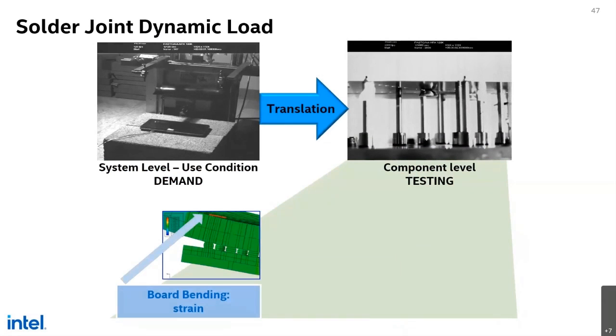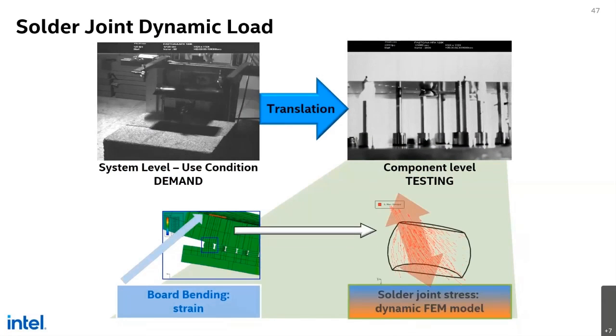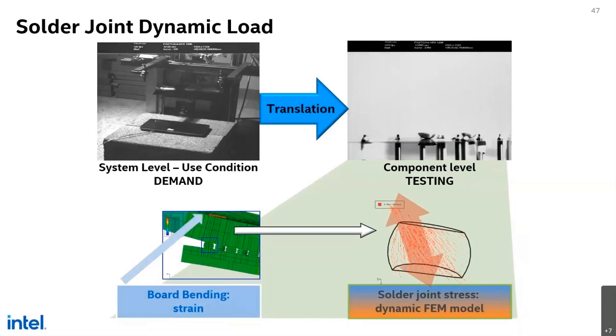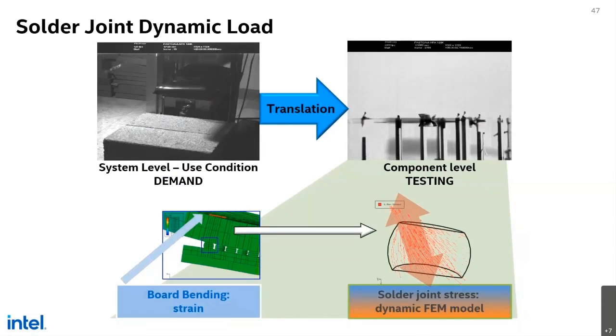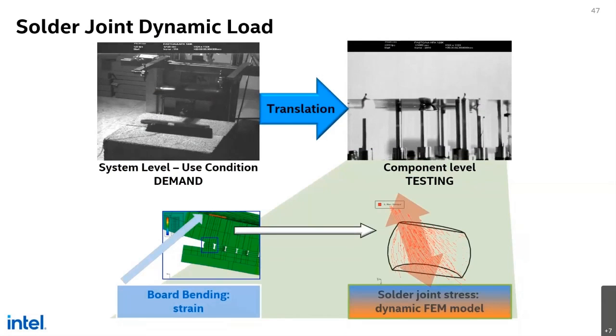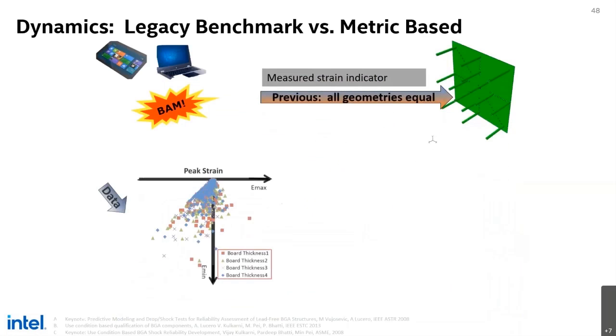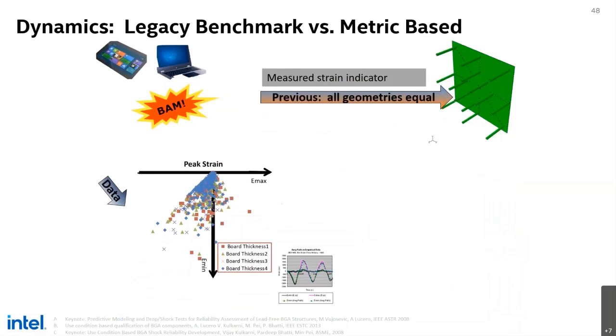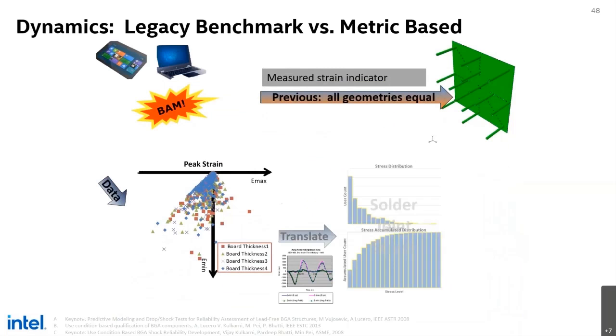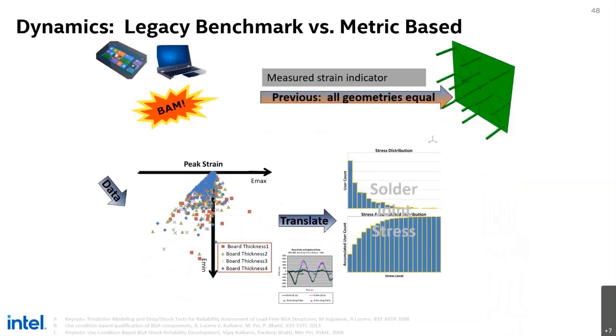So you can essentially compute and understand through strain measurements and computational means what kind of stresses you're imparting, and you can essentially come up with some kind of a stress. If you can measure that stress and model it in time and validate that stress applied over that time is good, then you should be able to then optimize the stress distribution. And you should know when you'll fail, and you can design that way for a particular environment. And then set your requirements.